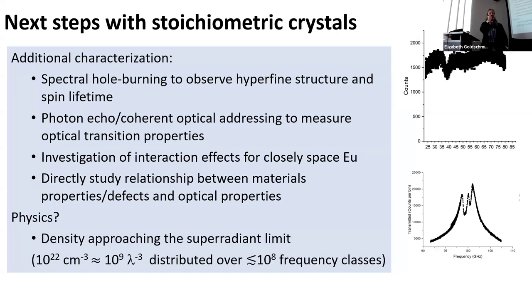So like I said, our spectral density here is really, really high, right? Our physical density of europium atoms in these crystals is approaching 10^22. That is definitely higher than anybody else has in terms of physical density of atoms or atom volumes, right? We still have inhomogeneous broadening, so the spectral density isn't quite that high.